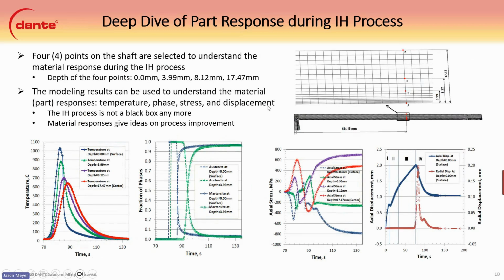Continuing with the deep dive, we can see the part response during the induction hardening here. So 4 points were selected on the model to show the depth. We have one on the surface, one at about 4 millimeters down, one at about 8 millimeters down, and then one representing the core. And these 4 plots here show the effect on the material as the inductor passes over and it is spray quenched.